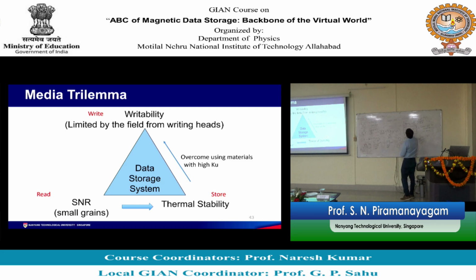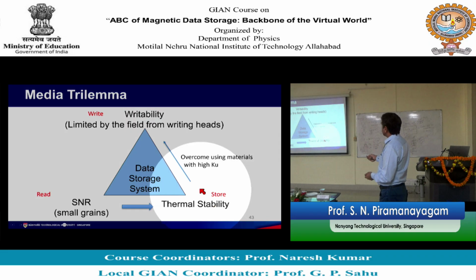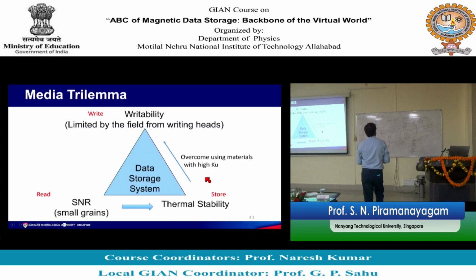We need to achieve a KUV by KBT ratio of 60. Okay. So what we have done is we have kept on reducing the volume. Right? When you keep the KU fixed, you keep reducing the volume, you are going below 60. So you can overcome this problem by increasing the KU. Okay, suppose you have, let us say, cobalt, chrome, platinum with an anisotropy of say 2 times 10 power 6 erg per cc. Suppose you come up with another material, let us say less chromium or something, and that material has a larger anisotropy constant, then you can double the KUV by KBT, right. So, if you can increase the KU, you can overcome the problem.